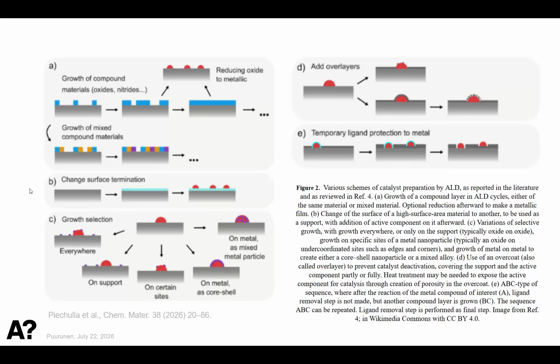One can also imagine to change the surface termination. So if you have a material that it's difficult to obtain in high surface area form, you may imagine that you create a thin surface layer on a high surface area scaffold and then use that to place your catalytically active materials. This is how I did my thesis in 1998 to 1999 to 2002, where growing aluminium nitride was the goal, and then we placed catalytically active metals there.